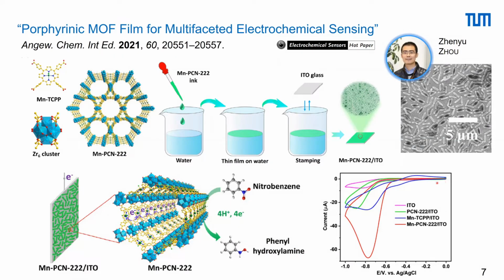And this gives you in the cyclic voltammetry this kind of big red trace here, and that would be the manganese PCN-222 ITO electrode, and the other traces refer to the blank ITO, the porphyrin without the manganese, then the manganese methylated porphyrin. But you see between the methylated porphyrin and the one integrated into the MOF a big difference, and this has of course to do with the kind of porosity of the material and the accumulation of the analytes close to the reaction centers. So this is the kind of work we do, combining thin film work, MOF work, and electrosensors application.